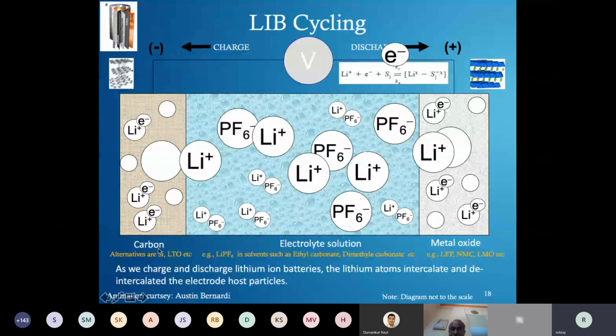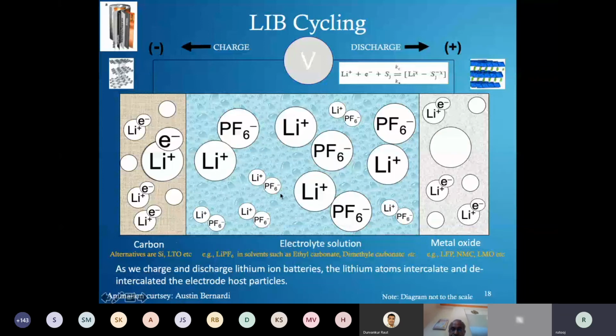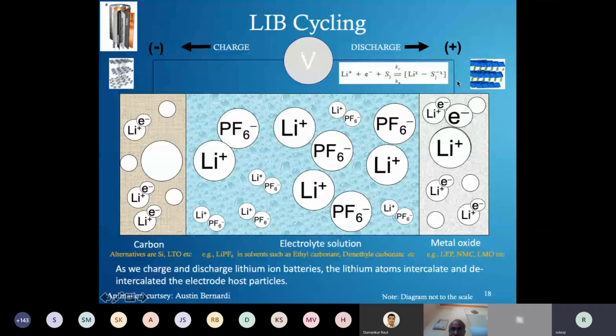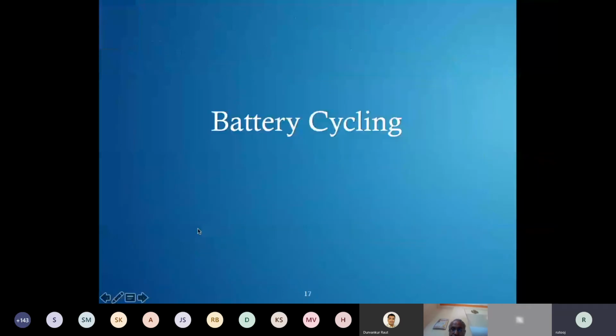The other positive thing about lithium titanate is that the potential of the electrode is 1.5 volts. We looked at the stability window of the electrodes. Our normal graphite electrode is much lower than 1.5, which means reduction reactions will happen on it. But lithium titanate is very close to 1.5, which means the rate of side reactions is minimal, or there are no side reactions theoretically. So that also gives much longer life than, let's say, a graphite based cell of NMC or LFP for that matter. The only disadvantage is, of course, cost and energy density.